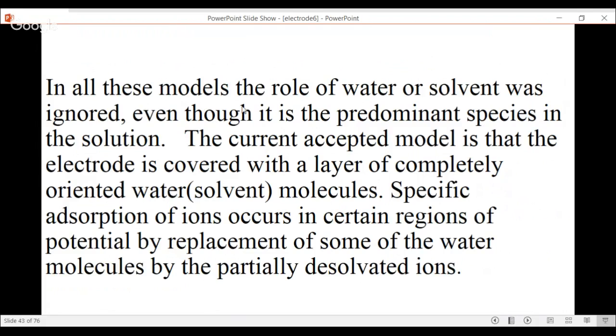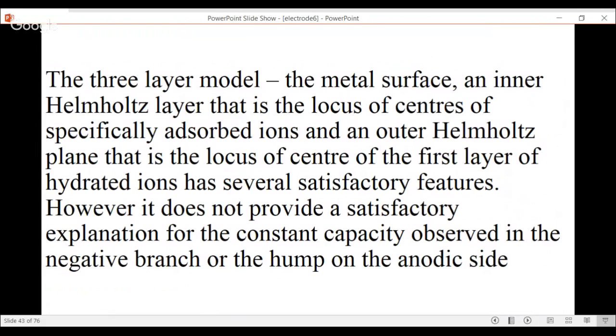In all these models, the role of water or solvent was ignored, even though it is the predominant species in the solution. Even if you take 10 to the minus 3 molar, the predominant species in the solution is the solvent molecules. The current accepted model is that the electrode is covered with a layer of completely oriented, polarized water or solvent molecules. Okay. Specific adsorption of ions occurs in certain regions of the potential by replacement of some of the water molecules by partially desolvated ions. Okay, we will see this.